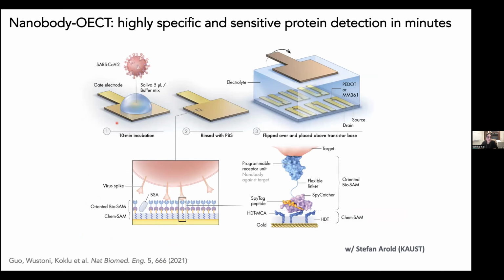Now, this is how the sensors that we build operate. So this is the gate electrode of the OECT, again, an external gate electrode, which we expose to the patient sample. And this can be patient saliva that is unprocessed. It's just mixed with a buffer that we produce in the lab, about 5 microliters of it. We just put it on the gate electrode surface. Next thing we do, after 10 minutes of incubation, we rinse off anything that is unbound by using PBS. And afterwards, we just take the gate electrode and flip it and put it on top of the transistor base. And the only contact between the two is the electrolyte that we use.